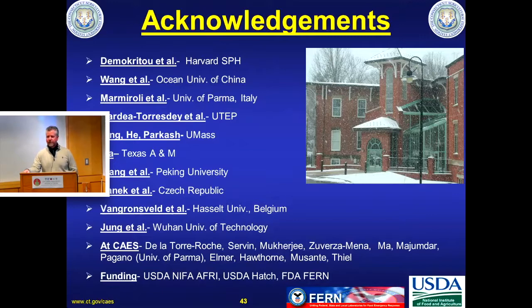And a comment about what you said about copper. We've seen exactly that with cerium oxide nanoparticles, where we put in nanoparticles, we then find them somewhere else, but they're not the same particles. The cerium oxide has dissolved and then has been bioprocessed to create new cerium particles, rather than cerium oxide, they're cerium phosphate or something like that. So it's true, just because you see particles in one place and you see them again doesn't mean it's the same particles. Exactly. I'm completely convinced this process, whether it's in plants or people, is completely dynamic.